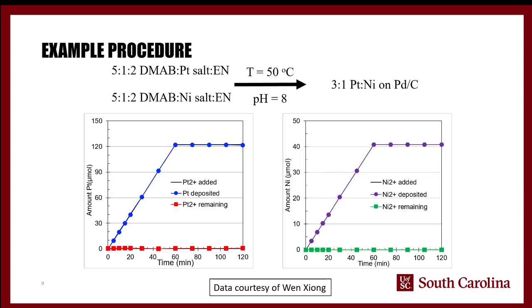And so here's an example procedure. So one of the metals that we used with platinum was nickel. In this case, the reducing agent was dimethylamine borane, with the platinum salt, and then ethylenediamine as a stabilizing agent. Basically, ethylenediamine will coordinate with the metal cation, and so it slows down the rate of deposition. And so what Wynn here did is she would actually pull aliquots during the course of the reaction,